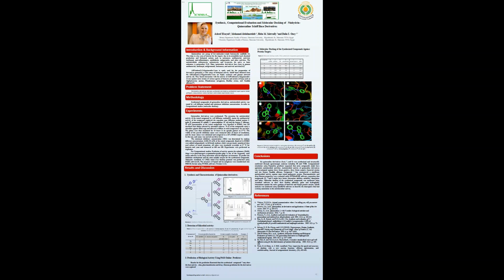Results and discussion. 1. Synthesis and characterization of quinoxaline derivatives. The condensation reaction of indenoquinoxalinone 1 with the corresponding aromatic amine in boiling ethanol containing a catalytic amount of glacial acetic acid afforded compounds 5a-d, where their structures were confirmed by spectroscopic analyses. The attempt to synthesize derivative 7 and carbothioamide derivative 9 could be achieved via the condensation reaction of quinoxaline derivative 3 with phenyl hydrazine 6 and thiosemicarbazide 8 in Scheme 1. In the proton NMR spectrum of compound 5d, the thiol proton appears as a singlet signal at 7.46, Figure 2.